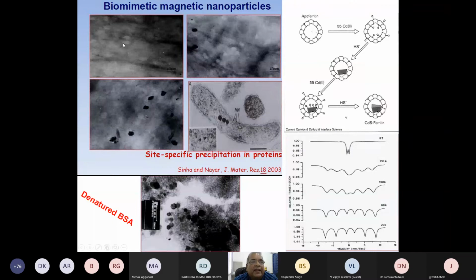We took bovine serum albumin, dissolved it in the water, and allowed it to form a gel under clean conditions at ambient conditions, at room temperature. Once the gel is formed, we dehydrated that and put it under the transmission electron microscope. If you look at this slide, where I am roaming my cursor, you will see there are the elliptical cages. So we thought that yes, we have arrested those cages present in the protein quaternary structure. But how to ensure and utilize it?